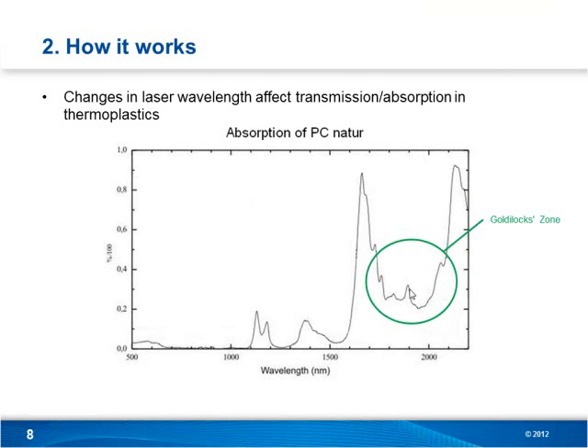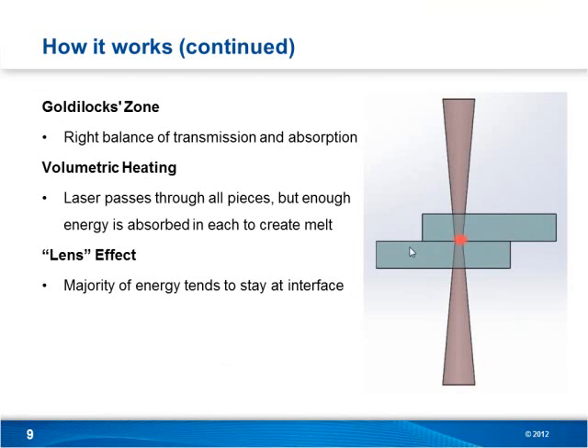It's about 50-50, not quite. In this case, we're not absorbing too much of the laser energy that we can't still pass it through to the lower layer, but we're absorbing just enough to get volumetric heating through the plastic. So here's a cross-section of what it would look like. Again, we have the right balance of absorption and transmission. So we can pass the laser through one piece and you're still going to see laser radiation make it through to this lower layer. But that being said, we're getting volumetric heating throughout the parts.